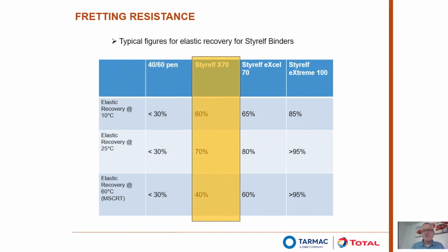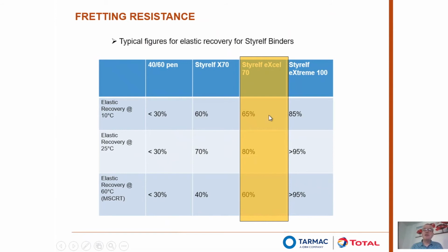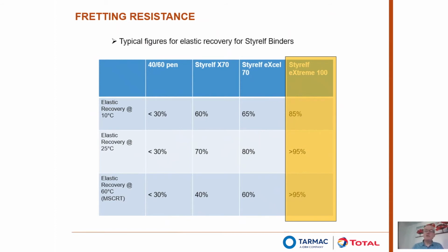If you now consider the X70, you can see that you're getting significantly higher elastic recovery at 10 degrees, much more at 25 degrees, and a little bit more at 60 degrees C. So it's quite temperature susceptible. Move towards an eXcel 70, you've now got 65% recovery down at 10 degrees, 80% at 25 and 60% at 60 degrees C. So we're starting to improve that elastic recovery all through the temperature range. And of course, Styrelf eXtreme 100, phenomenal amount of recovery, even down to 10 degrees and up to 60 degrees C. So that's why that type of binder is so good at resisting fretting from surface stresses.